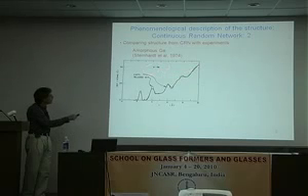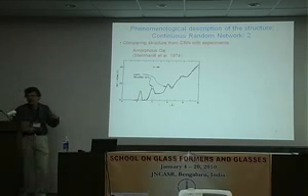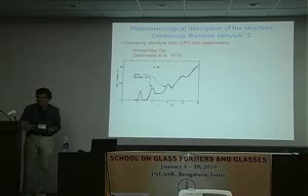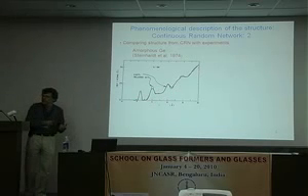And then the dashed line is the continuous random network, and the experiment is the full line. And you see that the location of the peaks and more or less also the height of the peaks is surprisingly good. And if you take into account the naivety of this model, it's just chemistry. Stick together and then don't care too much about angles, etc. You already understand quite a bit of the structure.